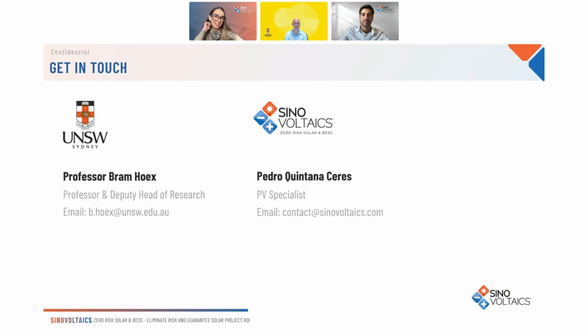And maybe another question from Anna, just a rhetorical one. As you mentioned that the modules can recover, if the recovery for UV-ID is complete after short light soaking, it shouldn't pose a problem in the field, as PV modules will recover fast after sunrise each day. Is that true? Yeah, it's true related to this dark storage degradation, which was initially reported. The values were reported after dark storage, and that was not representative of what you see in the field. So in the IEC test development, where I'm also involved, it's ensured that we test quickly enough after light exposure. So the UV degradation that's reported is representative of what you would expect in the field.